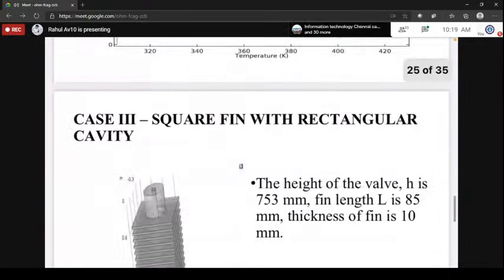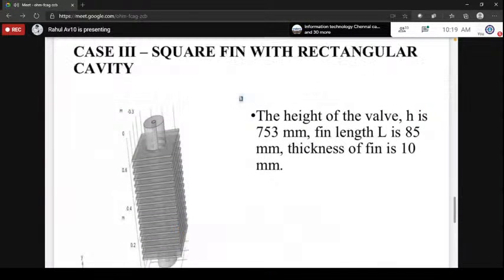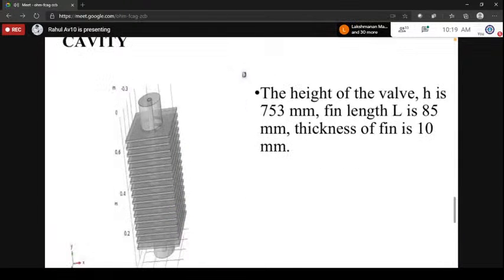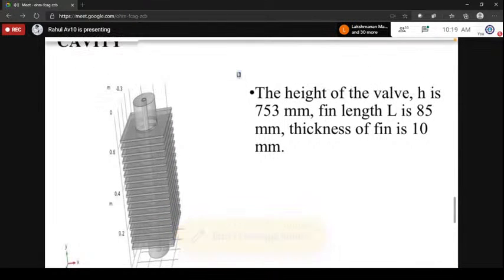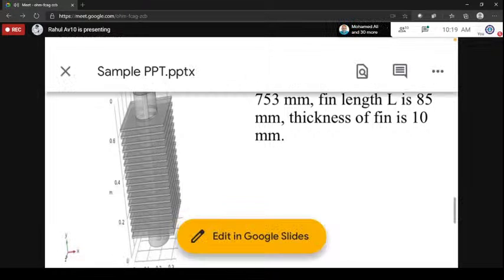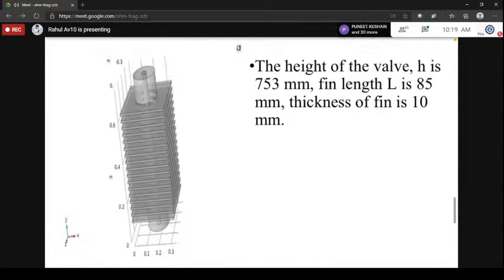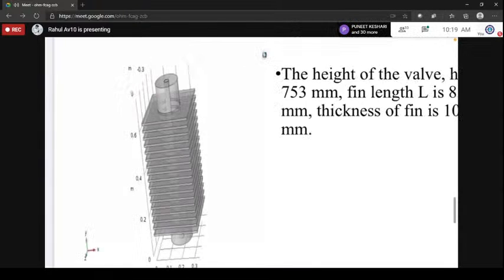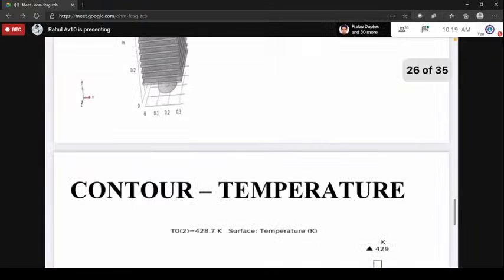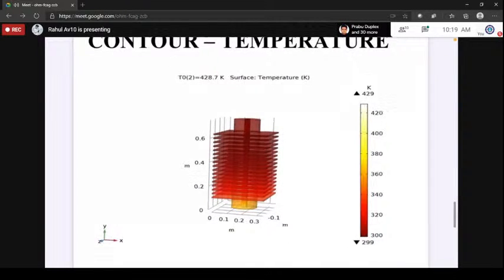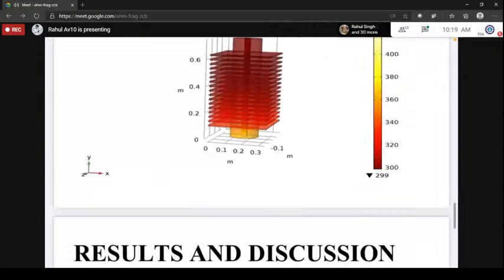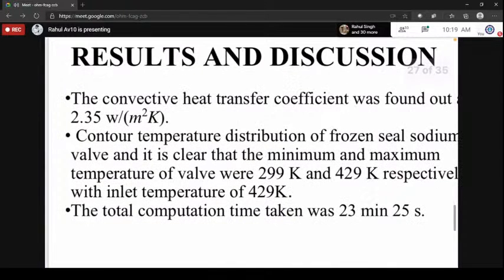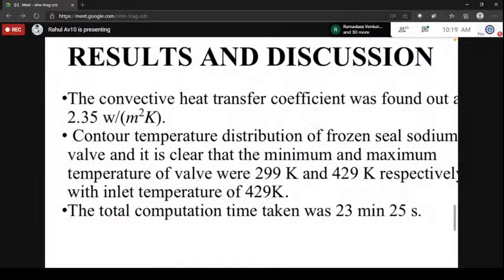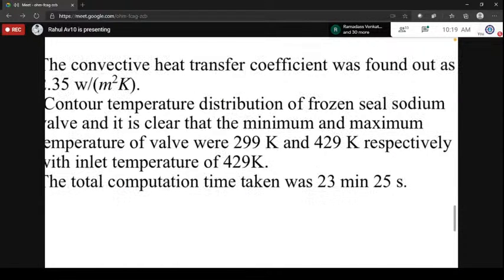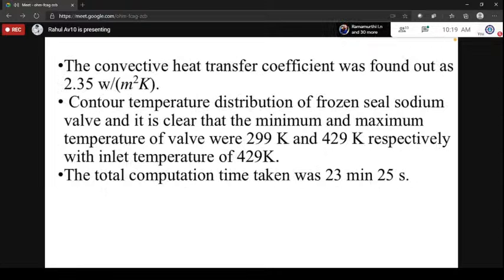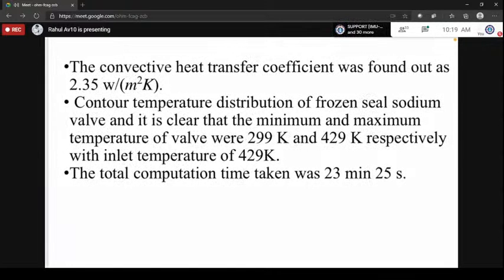And the final case is the square fin with rectangular cavity. In this case, the height, length and thickness are the same as the previous two cases, but the structure is different, as we can see it is a square fin, and it has a contour temperature similar to that of the previous two cases. And here the convective heat transfer coefficient is 2.35, and the minimum and maximum temperatures are 299 and 429 Kelvin, which is quite similar to the previous case.